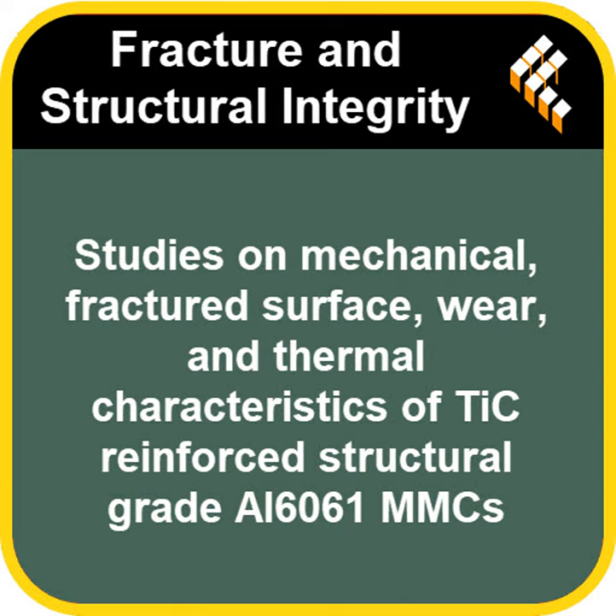However, similar to the mechanical properties we discussed, at 12 weight% TiC-Co, the thermal conductivity actually decreased again. Okay, that pattern is really consistent. Why the drop in heat conductivity? Same reason, agglomeration. It seems likely, yes. The reduction is again linked to the agglomeration of those ceramic particles. You can imagine these clumps hindering effective heat transfer. They might essentially shield the aluminum alloy matrix locally, creating barriers to smooth heat flow through the material, almost like tiny insulating pockets, as you suggested earlier.